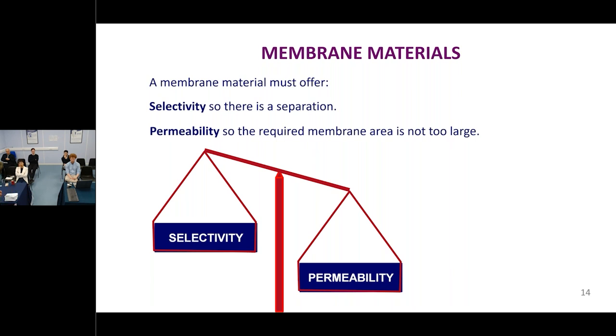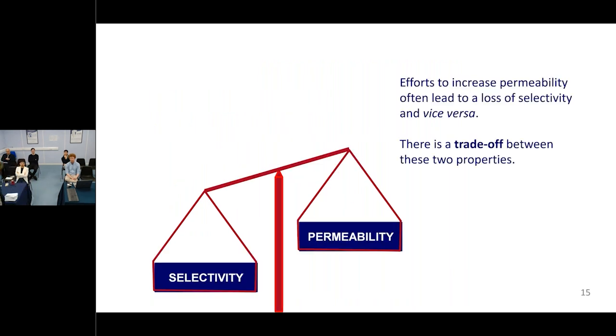But the thing about selectivity and permeability, and one of the frustrating things if you're a researcher trying to develop a new material, is you can put a lot of effort into trying to improve selectivity, and the trouble is you find you've lost permeability. Or you want something to be really permeable, and you find you've lost selectivity. So there's a balance, a trade-off between permeability and selectivity. And that's one of the first things we have to tackle. And usually in practice, we're finding an optimum balance, because we need a certain degree of selectivity. In fact, these days we're trying to push up the selectivity, because one thing we have done in our research is to find ways of making membranes that are much, much more permeable than we used to think was the case.